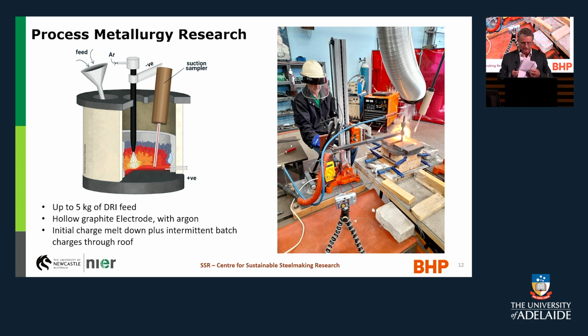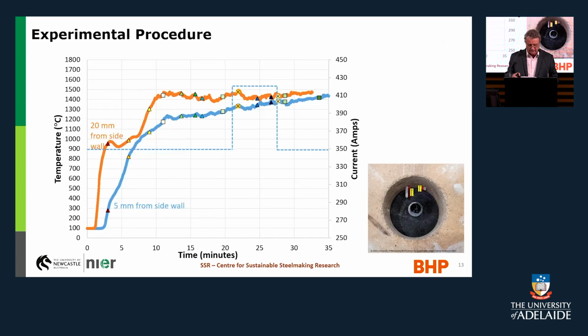Okay. So a little bit more about what we've done at Uni of Newcastle. And of course, one of the challenges of trying to do these experiments is that because you've got such a hot zone of heating in the middle of the reactor, measuring the temperature is a real challenge, right? So trying to measure the temperature anywhere under that arc heated volume is just impossible. But we can measure temperatures over by the sidewall and a little bit in from the sidewall. Okay, so that's what you see in that graph there, giving you a bit of an idea about what the temperature profile looks like in a typical one of our tests.